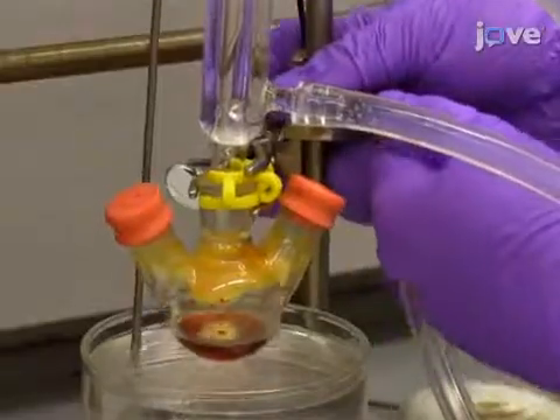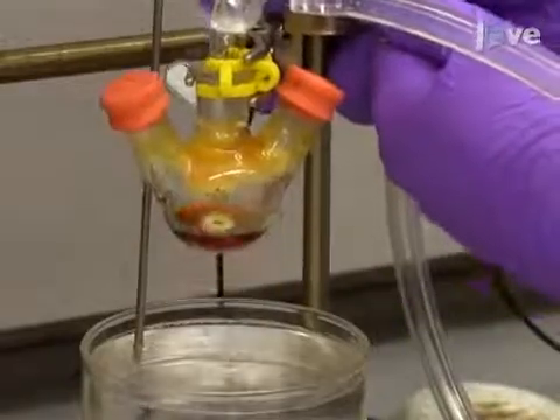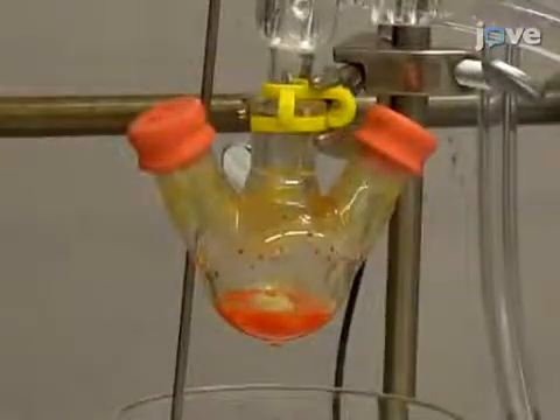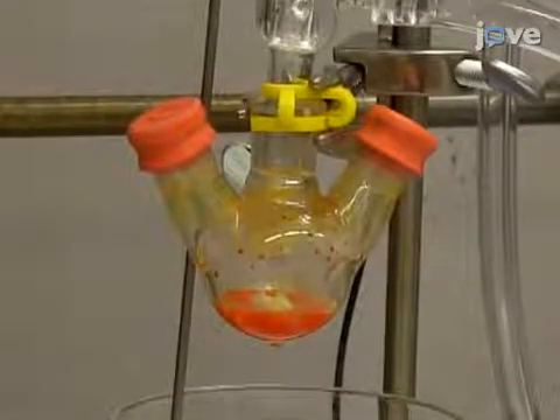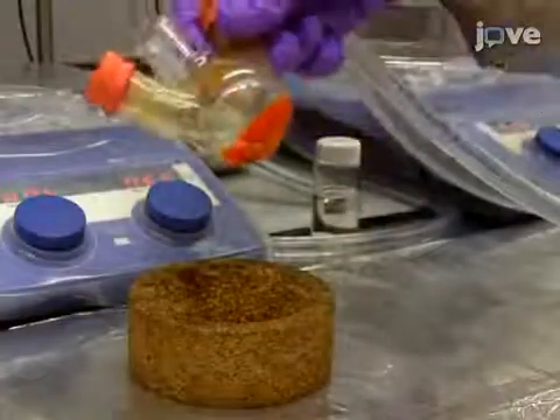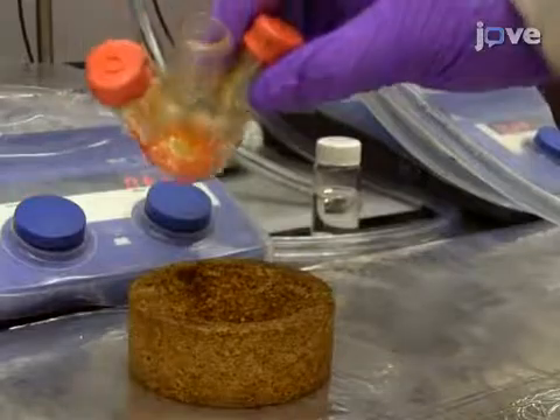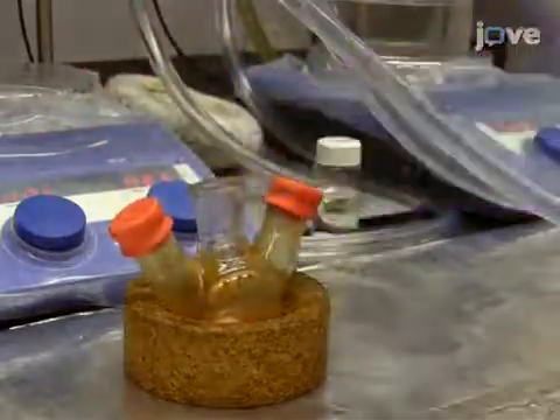Remove the solution from the heat and cool to room temperature. As it cools, the copolymer will slowly crystallize to form an orange rubbery solid. At this stage, the copolymer can be stored at room temperature for a subsequent synthesis, or it can be used immediately.